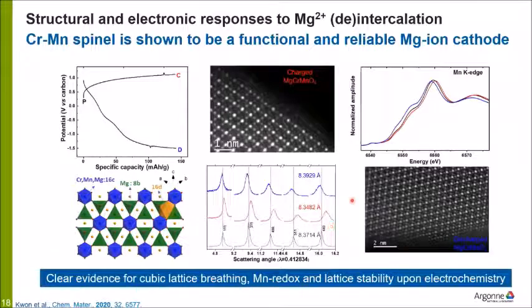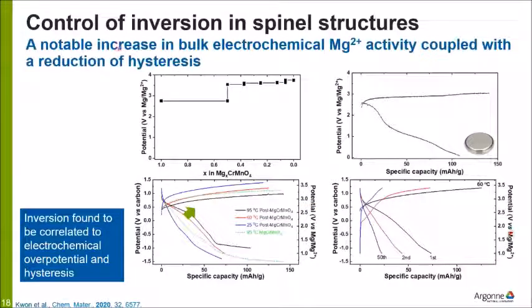It should be noted that the chromium itself is inactive in this structure. We are not activating the chromium redox center. So there's clear evidence for cubic lattice breathing, as you can see the sort of charge-discharge strain that we see. And then, as I said, the manganese redox is active, but not the chromium. And so we continue with this.